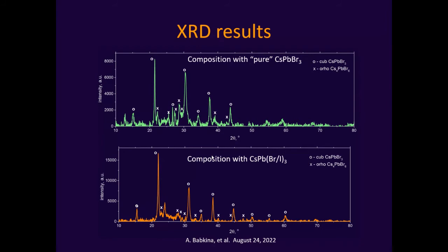If we look at the compositions only with bromine ions, we see that we have reflexes corresponding to the cubic perovskite phase and to the parasitic phase, cesium 4 lead bromide 6, but in less quantity. If we look at the composition with mixed bromine and iodine ions, we still see only the same phases. So what is it? Where is the iodine?